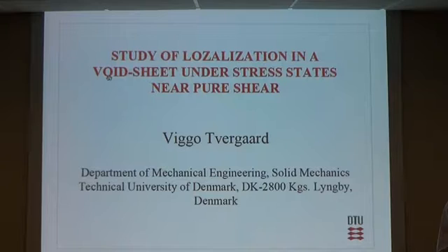This is an example of the results obtained. Looking at the ratio here, sigma 2 is 0, so here we have simple shear, and here we even have compression. The interesting thing in these previous results is that a maximum shear stress is actually reached. That means the voids explain final failure, even though the voids at this stage collapse to microcracks. From then on they are microcracks, but by interaction with neighboring voids they still give a failure by maximum stress.